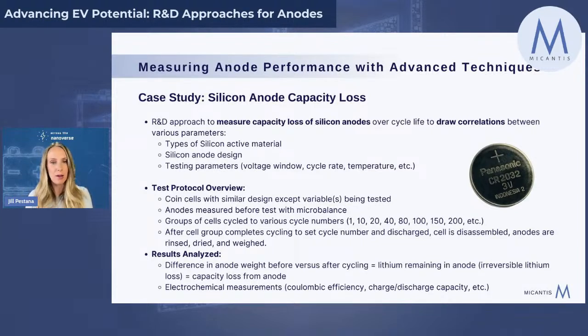the anode itself. Now, because silicon has such high energy density, the weight change of the anode before cycling and after cycling is the amount of lithium that's trapped in the anode, especially if you discharge the battery before you disassemble it. You're getting the residual lithium that's stuck in the anode, which could be the SEI layer and such. So there's a lot of cool properties you can explore through this technique.